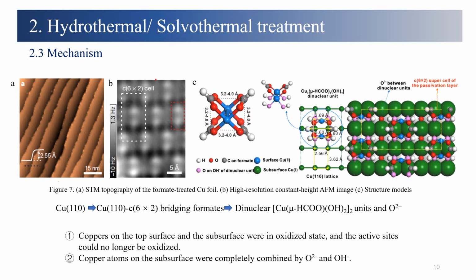After making sure of the structure of the passivation layer, it was obvious that while it can prevent oxidation, there were two main points. Firstly, the coppers on the top surface and subsurface were in an oxidized state, and the active sites could no longer be oxidized. Secondly, the copper atoms on the subsurface were completely combined by oxygen ion and hydroxyl. These two points made oxygen atoms or other adsorbers highly difficult to bind with coppers, leading to the anti-corrosion feature.